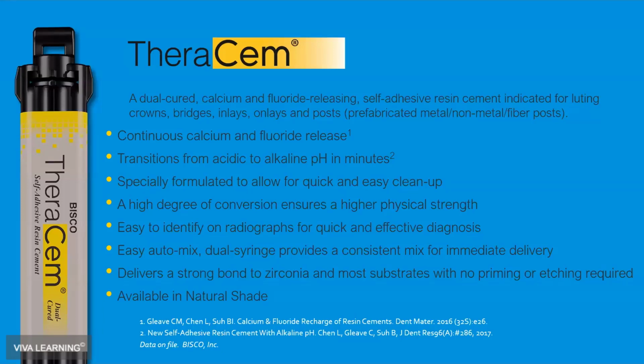That's basically to deactivate or use up the camphorquinone, which will help with any yellowing issues. But it also will help you maximize the strength of the material. So self-cure will work, light cure will work, but adding the light cure even to some degree is ideal. But Theracem also releases calcium fluoride. We cannot claim anything other than the fact that it does release calcium fluoride. It is a self-adhesive resin cement suitable for luting pretty much everything.